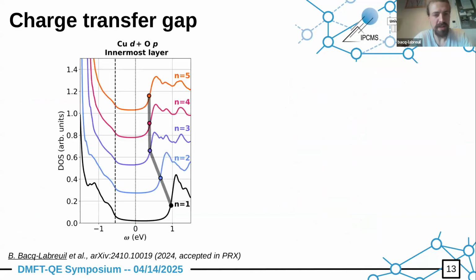All right, so let's start with the undoped system. So here is the NCCOC compound, undoped, so there is no doping. This is the stoichiometric compound. And I first show the charge transfer gap. So this is the density of states as a function of the number of layers, as you can see. And you can see that there is a charge transfer gap that basically diminishes from n equal 1 to n equal 2, and then from n equal 2 to n equal 3. And then it saturates